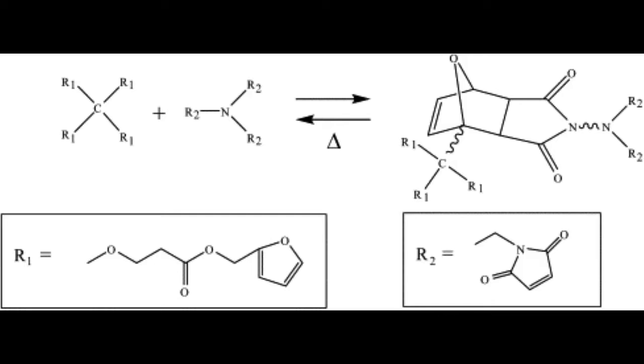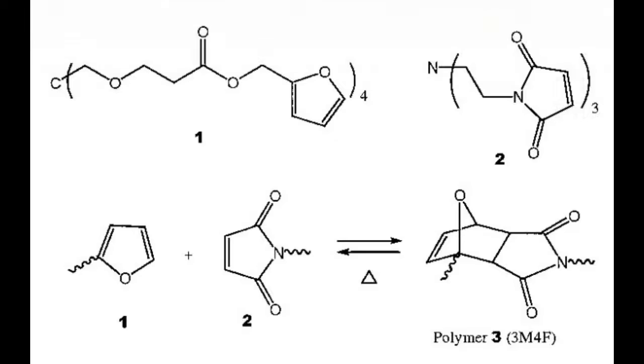These are sometimes not considered self-healing as they require heat to repair. Thermal energy breaks the covalent bonds in the polymer, forming smaller monomer particles that spread into the microcrack before the removal of heat allows the cross-linked polymer to reform into its original shape, effectively removing the crack. An example of this category of regenerative reactions is between multifuran, molecule 1, and multimaleimide, molecule 2. The reaction produces polymer 3, a highly cross-linked polymer with thermal reversibility.